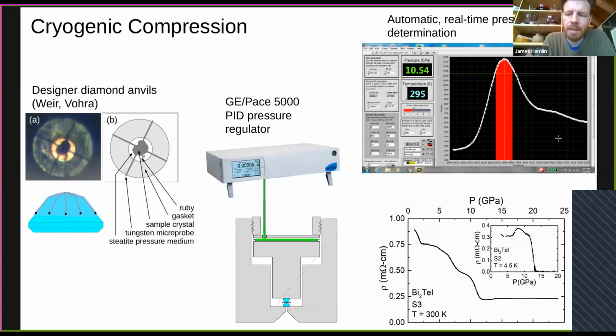And so, for example, one of the things you can do with this system is sweep the pressure at low temperature and see a superconducting transition as a function of pressure at constant temperature, rather than the common feature you see of sweeping temperature at constant pressure. And so this is something we've employed in a number of different cases. This one I'm showing here, bismuth 2 tellurium iodide, we actually discovered 3 different related materials, all that exhibited pressure-induced superconductivity. At room temperature, we find some other anomalies in the resistivity.